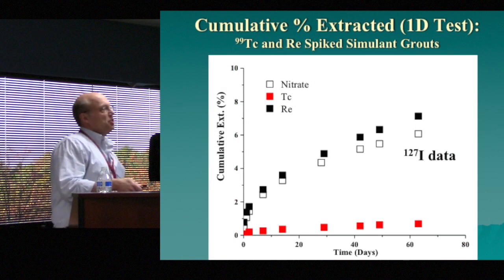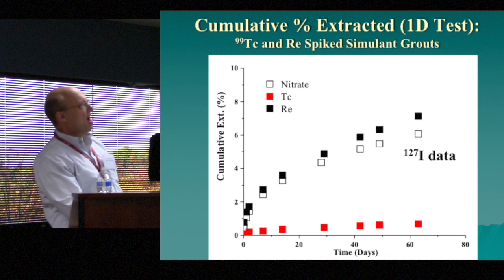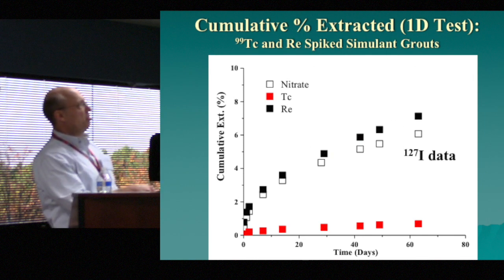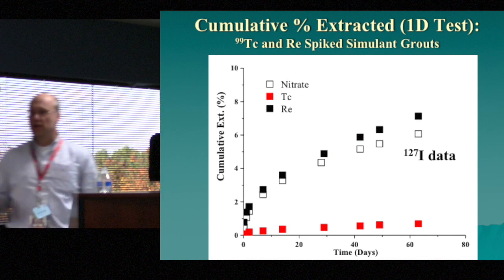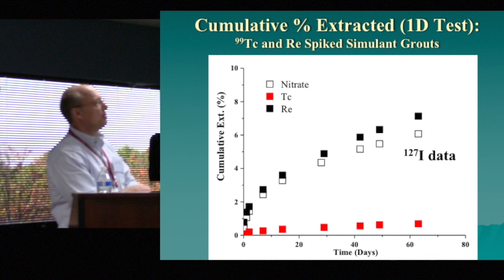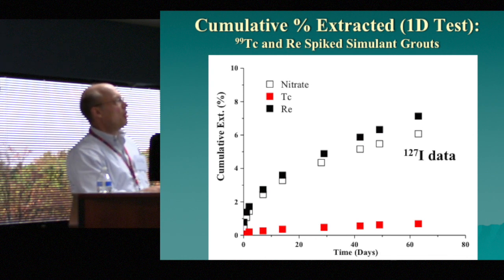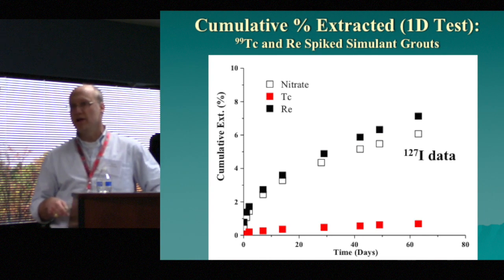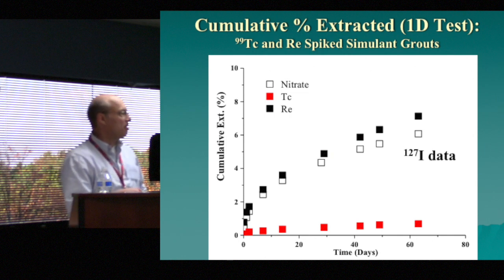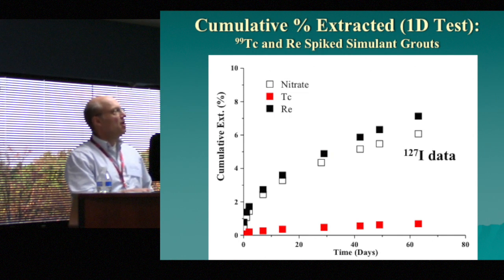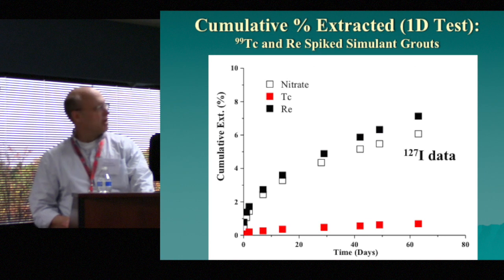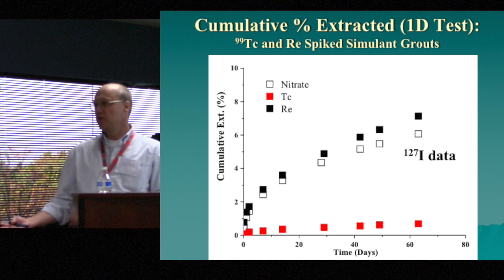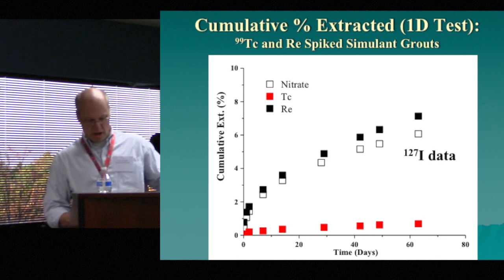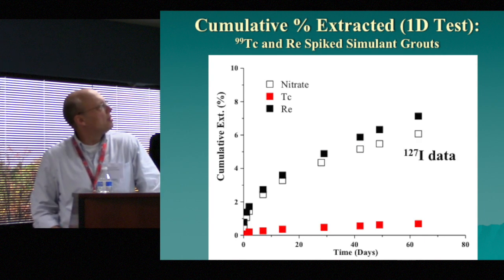So this is comparing just Tc-99 versus rhenium and nitrate. And this is cumulative extraction, so we have to have a very good idea of what our initial starting point is. But what you see is that both rhenium and nitrate come out of the sample at essentially the same rate in terms of their percentage coming out, while technetium is very low. I put the iodine 127 up here just to say that you see the exact same thing with iodine as well, even though I didn't want to make the graph so cluttered. Next slide.